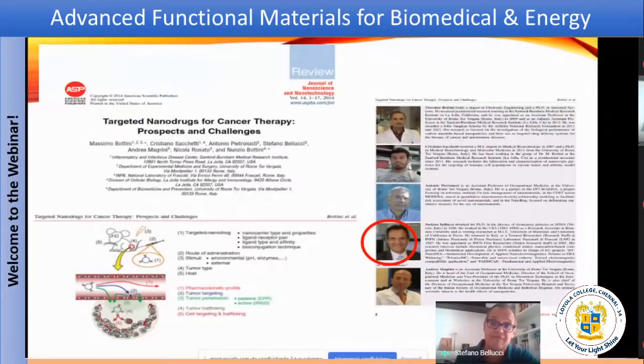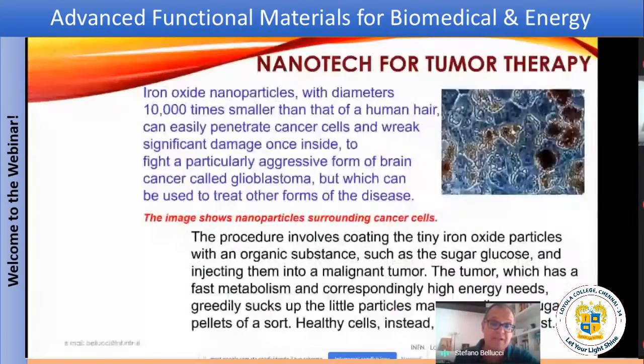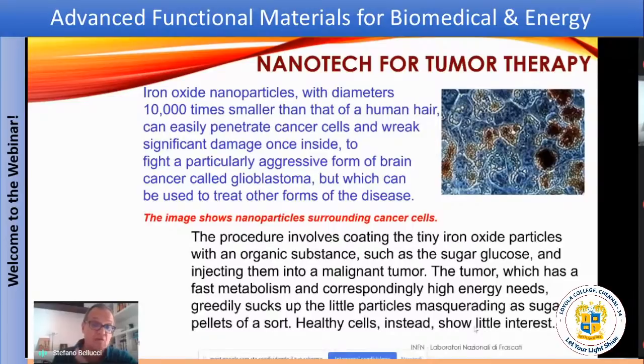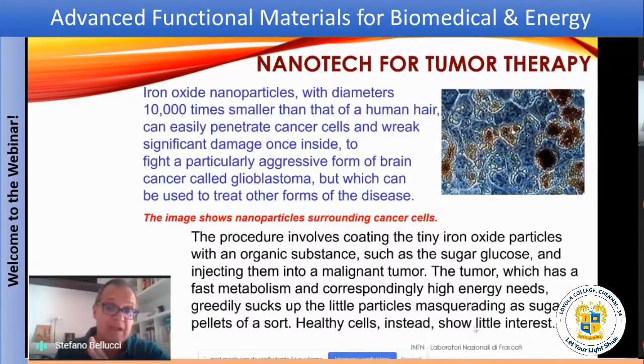Nanotechnology has been used since a long time for curing tumor. An old way of curing tumor is the hyperthermia. Basically, you heat up the tumor until the cells go into apoptosis, let's say at 45, 46 Celsius. But nanoparticles of iron oxide magnetized have been used in Germany at the Berlin hospital La Charité for curing prostate cancer, using the fact that nanoscience here gives you the specificity. So instead of heating up the whole tissue, tumor cells and healthy cells, thanks to the little tiny nanoparticles of iron oxide paramagnetic behavior, they can be put in an oscillating magnetic field, and only the tumoral cells, who are typically greedy and they eat up, so to speak, those nanoparticles because they are sugar-coated, only those malignant cells are being destroyed.